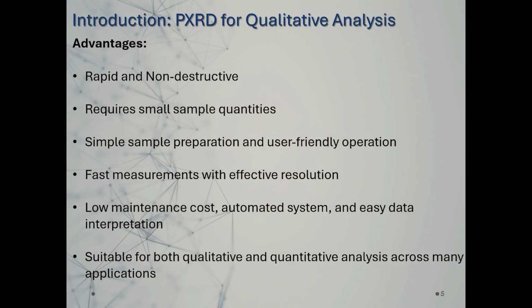What are the advantages of X-ray powder diffraction for qualitative analysis? It's a really rapid and non-destructive technique. By rapid, I mean more or less 1 day to get the data, and it is not destructive because the sample usually can be recovered. There are, of course, some samples that are really sensitive to X-rays, but these are few cases. It also requires a small amount of the compound that we want to analyze, 10 or 15 milligrams, and it is simple to prepare the sample. You just have to reduce your sample to powder, and then you fill a capillary. You can choose the dimension of the capillary that you want to use. It's also a fast measurement, and it's low cost.